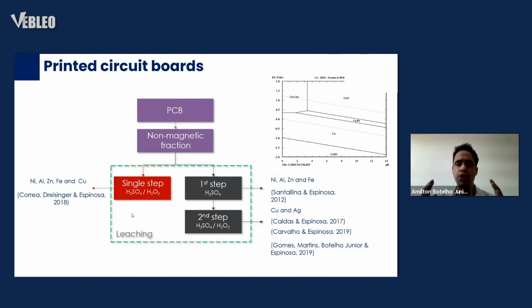Most of the literature uses concentrated nitric acid to obtain copper from PCB, but we found that it's possible to use a dilute solution of sulfuric acid, 1 mole per liter, less than 5% sulfuric acid, together with hydrogen peroxide to leach copper from the metallic fraction to the aqueous media. So it's possible to use diluted sulfuric acid to extract copper.